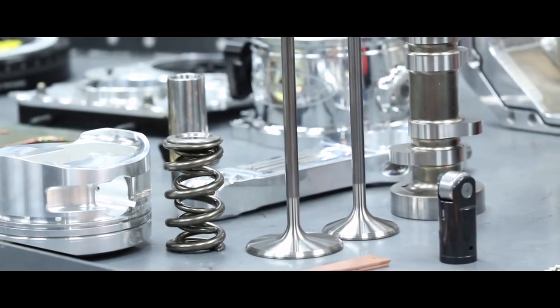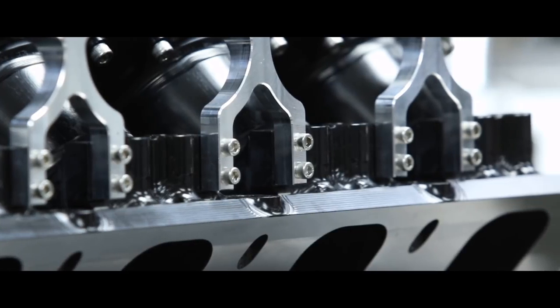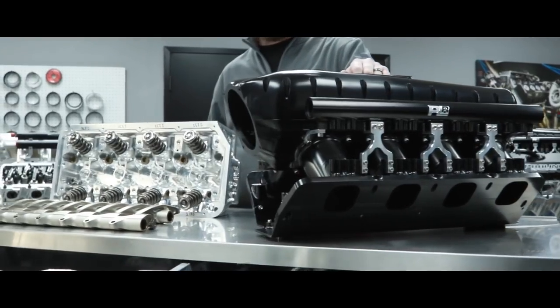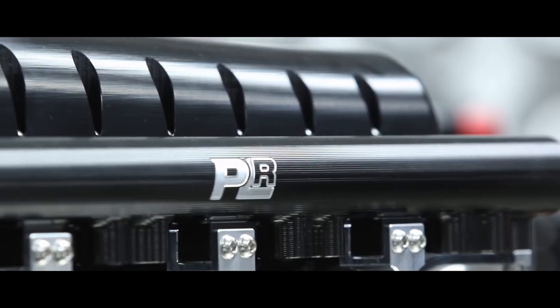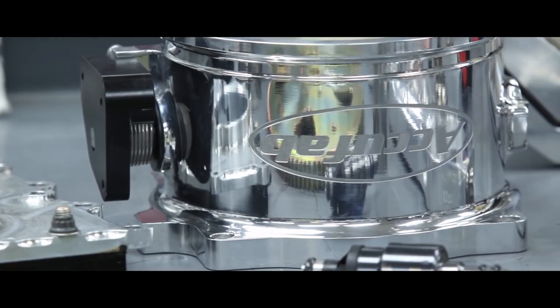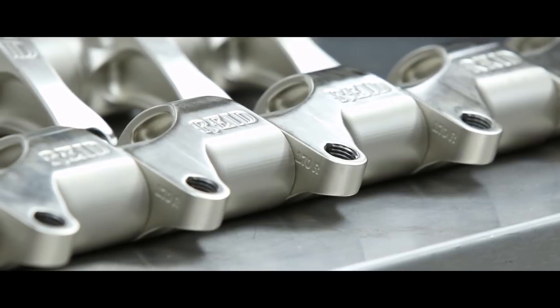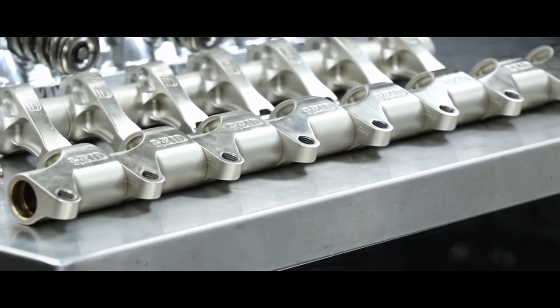Four valves in this particular engine — both titanium because it runs on alcohol. We don't have to worry about extremely high EGTs with alcohol. We actually have Trend pushrods in the engine currently. This particular engine utilizes a single-piece pushrod which has a tool steel insert in the cup end. This is our intake manifold — Visner actually works with us very closely on this. One of the big things for our intake is a large plenum volume, trying to get the air calmed down a little bit. On the front of our Visner billet manifold, we use a billet throttle body provided by AccuFab — this particular unit is a 125 millimeter single. We use Reid rockers on basically all of our Hemi engines: a billet steel rocker arm design that runs on a shaft, oils here with a bronze bushing and a roller tip.